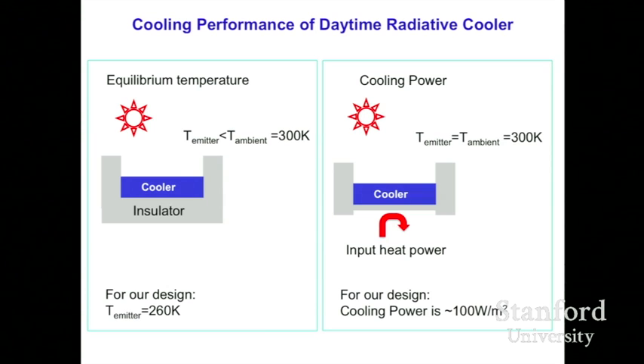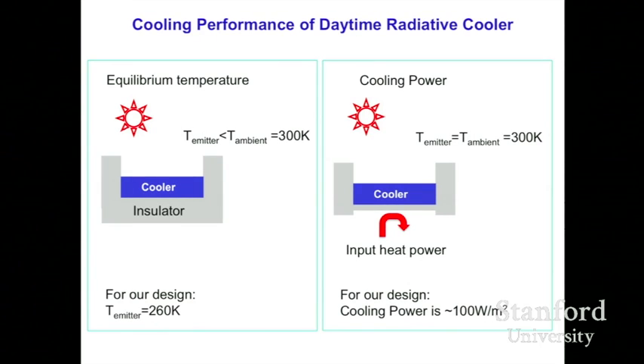In this case, it reflects most of the sunlight and therefore doesn't get heated up by the sun, but in the meantime, it radiates the heat out, so its temperature is going to go down. And using the spectrum that I've just shown you, both the emissivity spectrum as well as the transparency spectrum of the atmosphere, you can compute what the equilibrium temperature will look like. And for a 300 Kelvin ambient, the equilibrium temperature is on the order of 260 Kelvin, theoretically.